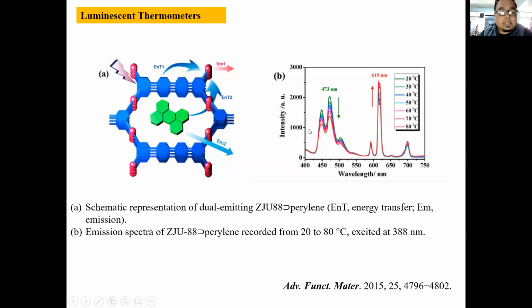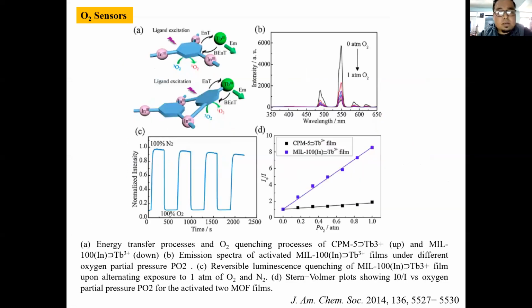So which can actually record how the temperature is changing. So all these devices have been made. The final one about its properties is oxygen sensors, which is also very good. Here, there's an indium-based MOF. In the indium-based MOF, terbium-3 ions are encapsulated, and the change in the quenching of the terbium emission when exposed to oxygen has been recorded. So this gives rise to a very good oxygen sensor.